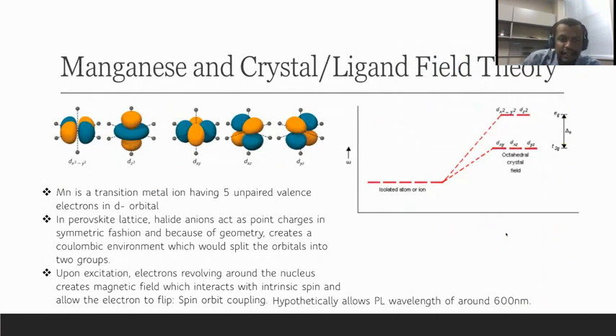So manganese is a transition metal ion having 5 unpaired valence electrons in the d orbital, and these orbitals have these shapes, or lobes, that we see in the figure at the top. That's for the manganese ion in vacuum, by itself. But in the perovskite lattice, we have halide anions, which are the ligands attached to the manganese atom on these axes that are shown in the orbital pictures.